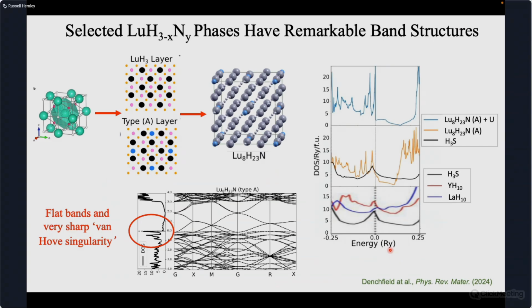Well, apart from the superconductivity, these are very interesting systems, and this is something that one of my students who just finished this past year worked on. You can build up this structure of this trihydride-like system, a substoichiometric trihydride, in some cases with nitrogen doping, and for different orientations or different stacking of layers, you can make very interesting crystal structures with very interesting band structures. This is not the structure search method. This is more or less old-fashioned building a structure with balls and sticks, but on a computer, and you can do a kind of band structure engineering.